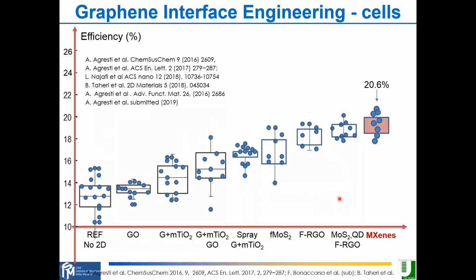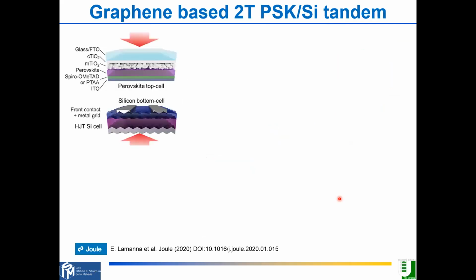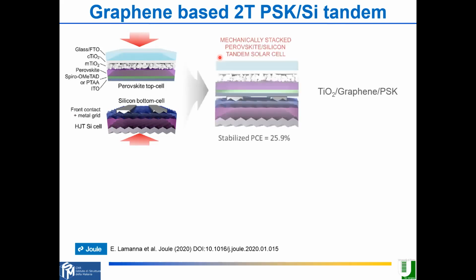There is an interesting point also pointed out by the Kaneka talk before, which is the tandem. How do we go from 20 up to, for example, more than 25, more than 26? We have proposed a very simple solution for the tandem, a mechanically stacked tandem. You take a conventional heterojunction silicon solar cell, the kind you can buy from a company. Then you create a top perovskite cell, which of course should have TCO on both sides, and then you mechanically stack the two.